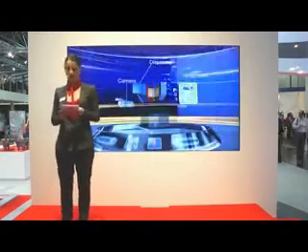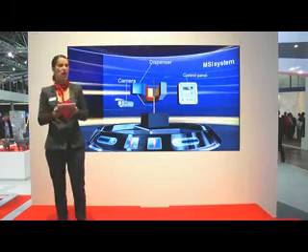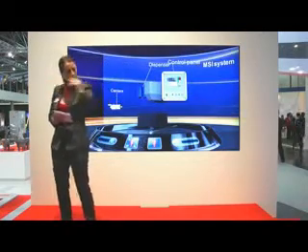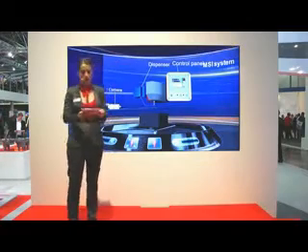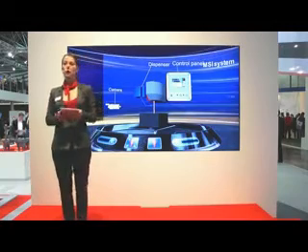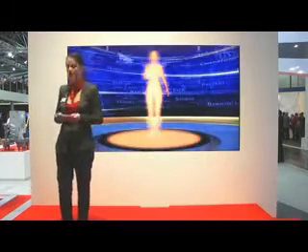The MSI metal stream inoculation system provides a final adjustment of the inoculation state of the iron. In order to achieve consistent solidification, a small quantity of inoculant has to be added to the melt — as late as possible, ideally as it enters the mold cavity. This is done by the use of a dispenser, a camera, and a control panel. The high and consistent quality of the MSI-treated ductile iron reduces foundry process casting, finishing, and cleaning costs. The entire foundry process benefits from better metallurgy.